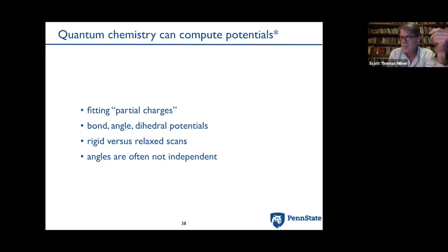And those, unfortunately, involve not just the properties of the ground state, but fluctuations into the excited state. And it's not an easy thing to compute that contribution for different atoms from simple quantum chemistry calculations. That's a present limitation of using density functional theory type calculations, which are really about the ground states of molecules, to compute those attractions.